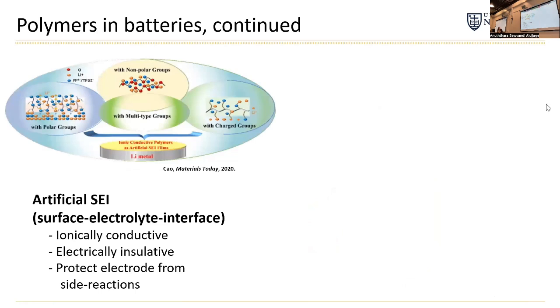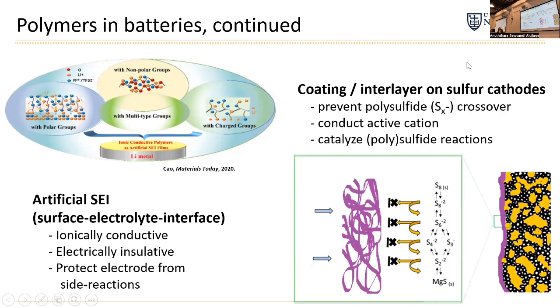And then there's been excellent work recently in the research literature on creating artificial SEIs or artificial interfaces on the surface of active electrodes. And so this is creating a surface layer in order to control the interfacial chemistry that happens. And this can be done with polymers as well. And then in sulfur type batteries, there's a lot of intermediate species that are formed. So my group and many others have been working on creating interlayers or surface coatings that modulate the transport of these intermediate species in the cell.